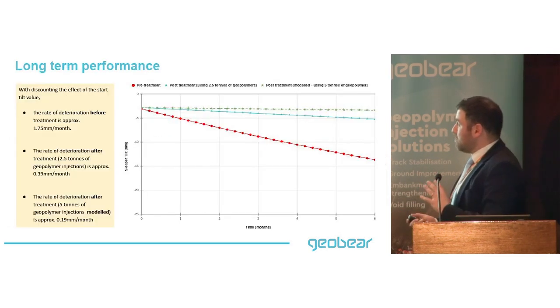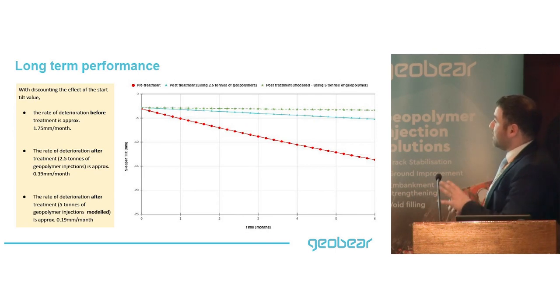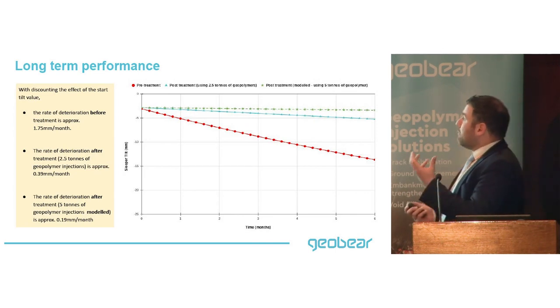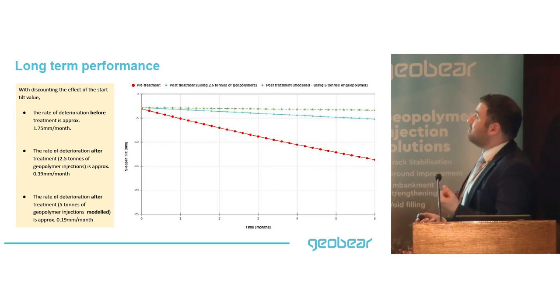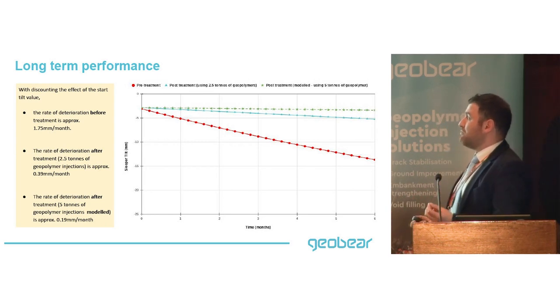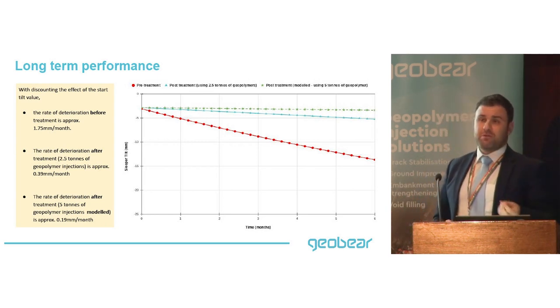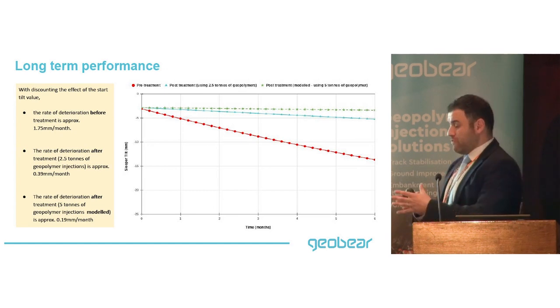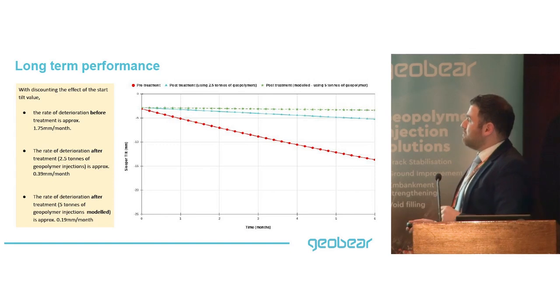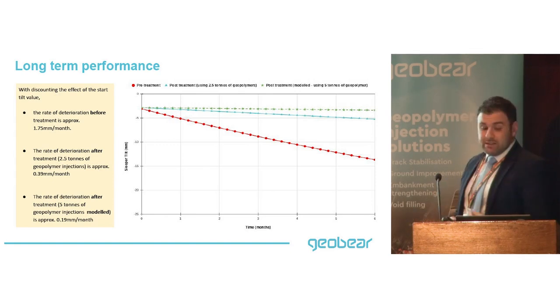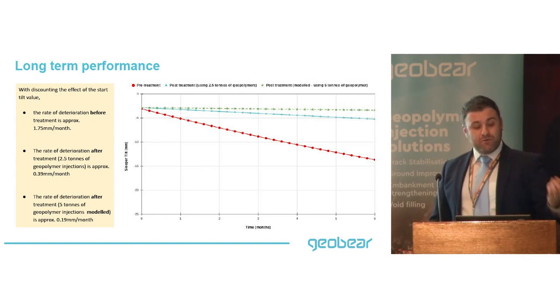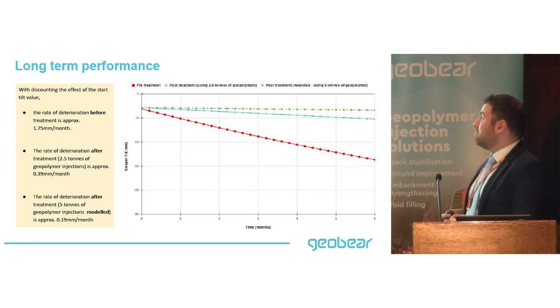Based on this, we managed to generate these processed graphs from the data, and what it shows is that before the treatment, the rate of deterioration was around 1.75 millimeters a month - so every month we were losing that much, a tilt movement by that amount. Following the treatment, we estimate this has gone down from 1.75 to around 0.4 millimeters a month.